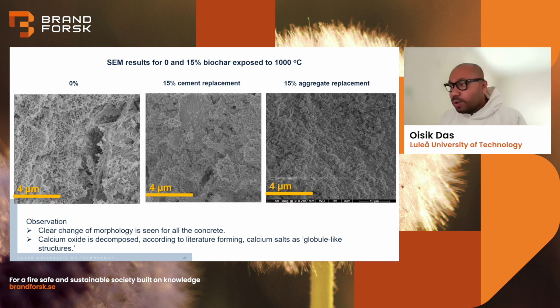And this is where things go a little crazy. These are the samples which were exposed to 1000 degrees centigrade in the standard fire curve ISO 834. So we see a clear change in morphology. We see globules. Basically what happens is the calcium oxide is thermally decomposed, it creates calcium salts, which are those globule-like structures. This is from our literature study, where we saw that these globule-like structures are basically calcium salts, which form due to the decomposition of calcium oxide.